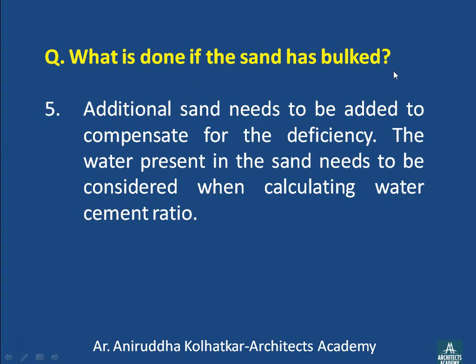If the sand has bulked, there is a remedy. We add additional sand to compensate for the deficiency. Also, the water present in the sand needs to be considered when calculating the water-cement ratio. When placing sand in the mix by volumetric method, we add some additional sand to compensate for the deficiency. Because water is already present in the sand, we reduce the amount of water added to the concrete mix to compensate for that additional water present in the sand.